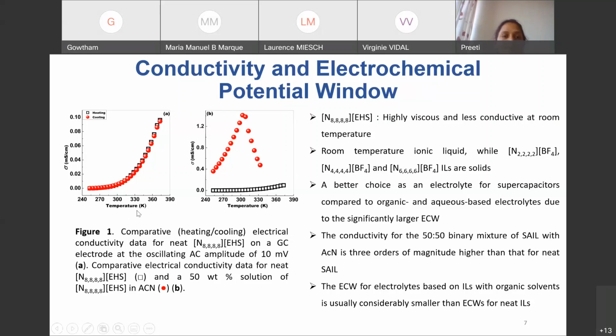And as you can see here, we have first measured the conductivity of the neat N8,8,8,8 EHS ionic liquid. You can see we have done it for both cooling and heating, from very low temperature up to 100 degrees centigrade, 373 Kelvin, and it increases. And it's highly viscous, so we thought to reduce the viscosity.